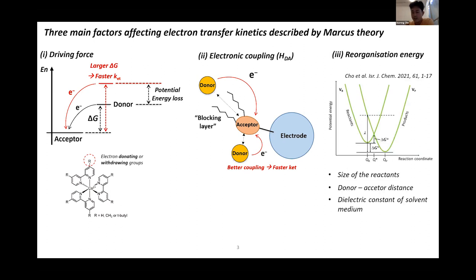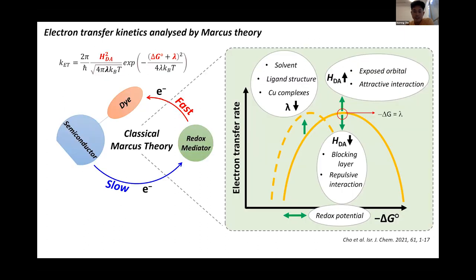The other thing is the reorganization energy, which is basically the energy required for electron transfer to make the geometry of the reactants the same as that of the products. It is affected by the size of the reactants, the donor-acceptor distance, and the dielectric constant of the solvent medium. These can be determined by measuring the charge transfer rate and plotting it as a function of delta G. So the most important thing here is to determine the fastest charge transfer rate using